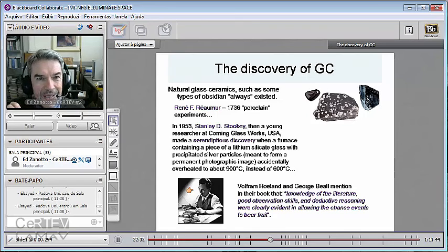And, okay, he saw the mistake and tried to pick that glass sample out of the furnace, but the glass dropped on the floor and did not shatter. Did not shatter. So I'm starting to answer that question. Glass ceramics in general are much stronger than glasses. It had crystallized on top, crystal phases formed on top of the silver particles which were dispersed in the volume of the glass, and he made the first artificial glass ceramic in 1953 or so.